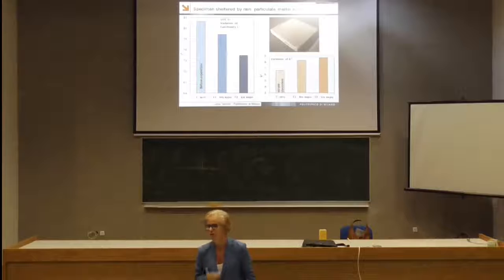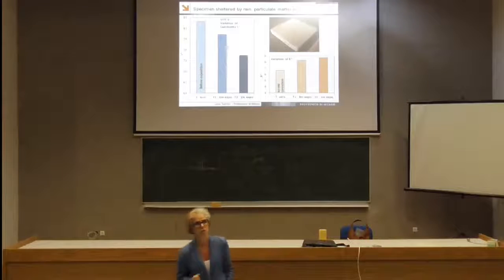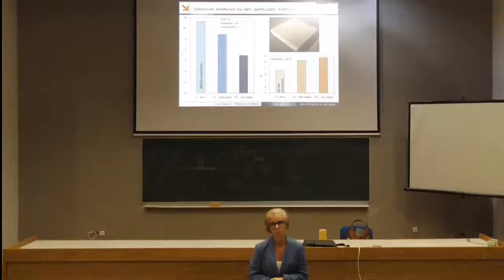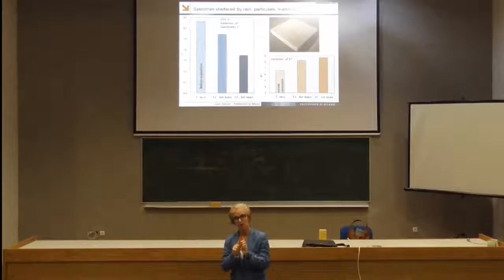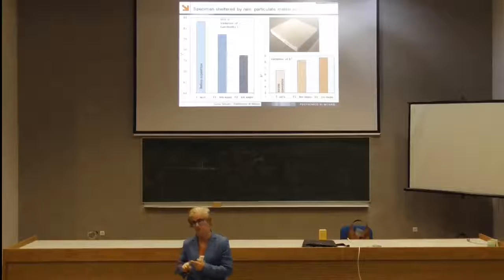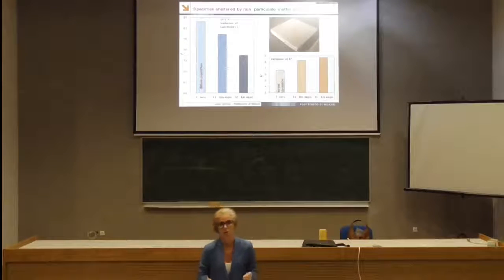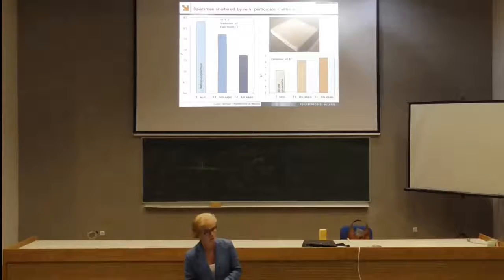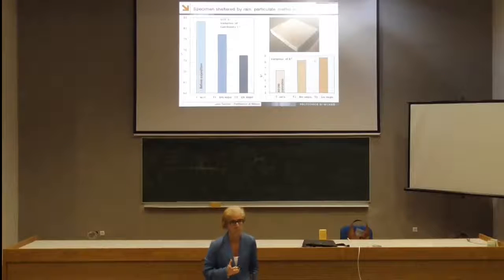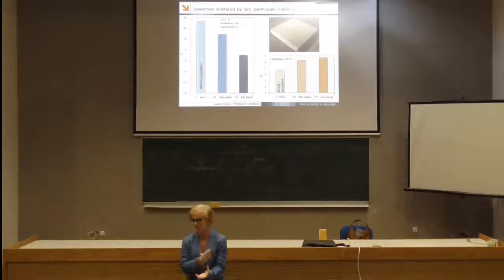When I say that the surface is changing very fast, it's because my experience says this. And what about yellowing? Because you know that the climate change today is that we probably have 1 or 2 centigrade more, medium more. And we accumulate organic materials, volatile organic materials on the surface. So that is not only a matter of darkening of the surface, but at the same time is a matter of yellowing. So our surfaces are becoming more and more dark, more quickly, and more yellow. And this is clearly visible also in the same period of time in 1 year, because if you have the new specimen you can see it very quickly.